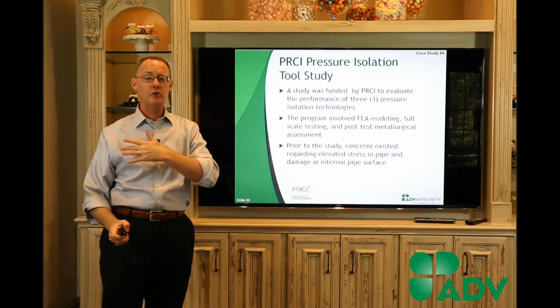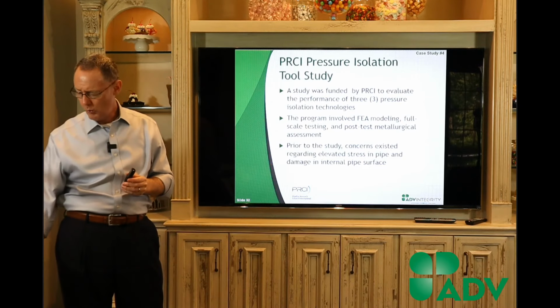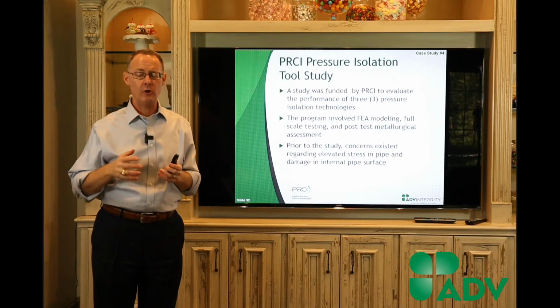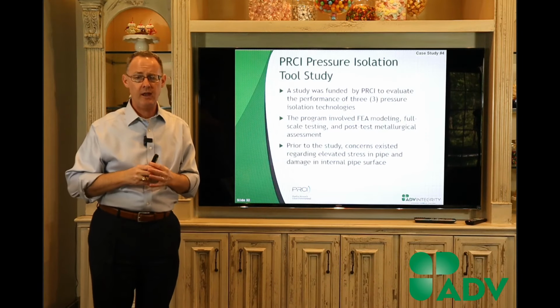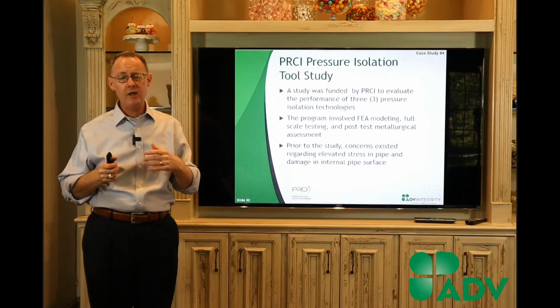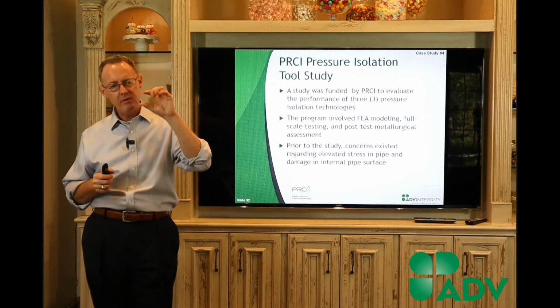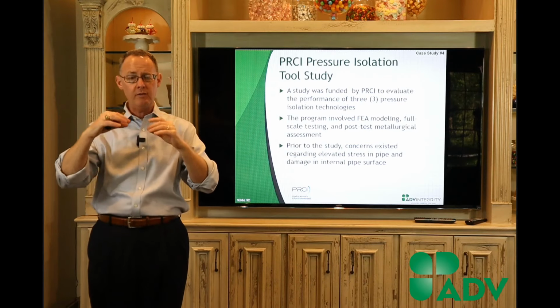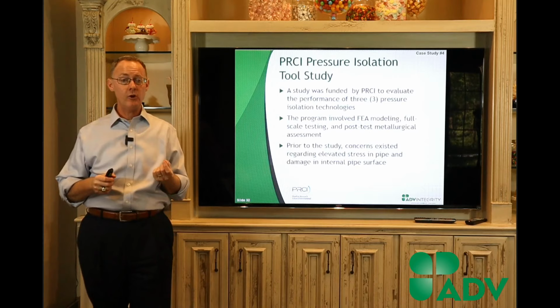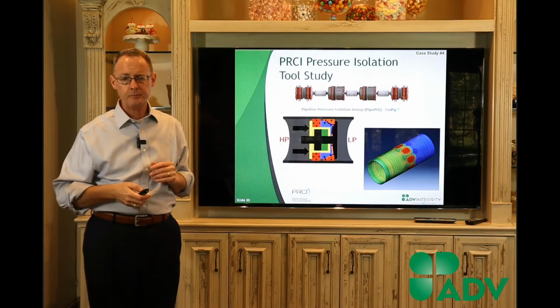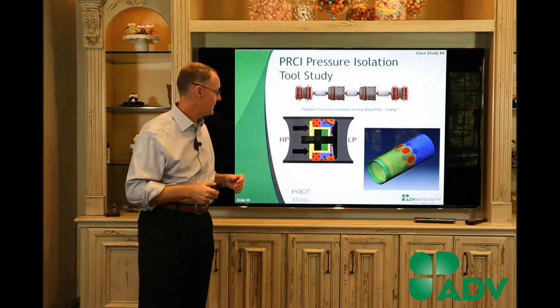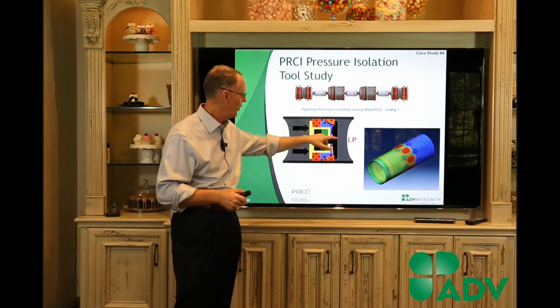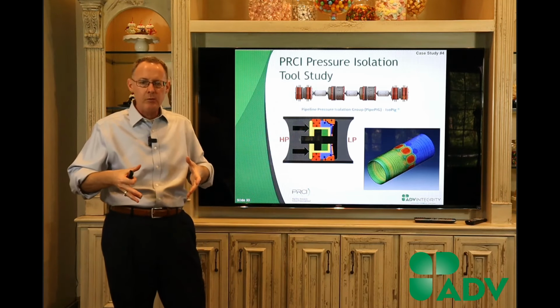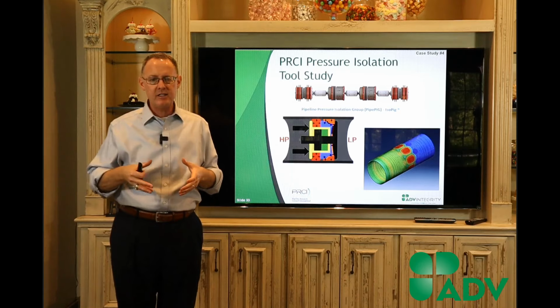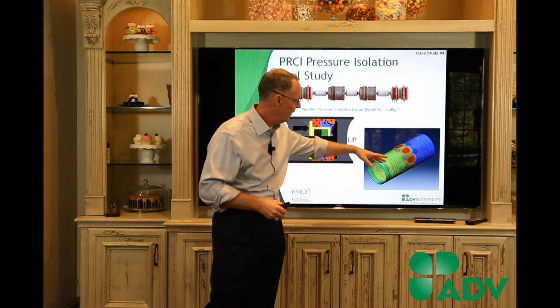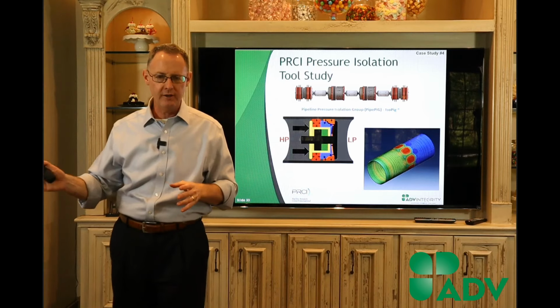So one of the concerns, these are used offshore a lot. One of the concerns onshore was that we would have very high pressures or very high stresses, created due to the elevated stresses because we have thin wall. And if you've done any offshore pipeline work, offshore pipelines tend to be very, very thick because of the concerns of the compressibility of the deep water environment. Onshore, we tend to have thinner wall. And so these tools come in and they set. And so we built a bunch of FEA models of this. This is kind of a little schematic. So you have a high pressure side, a low pressure side. As this tool sets, it expands in place, and it has to lock itself in place so it creates stresses. So we've got some images here, and if you've done any FEA, red bad, blue good. It's pretty simple.